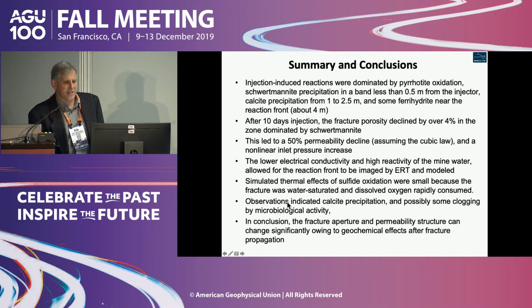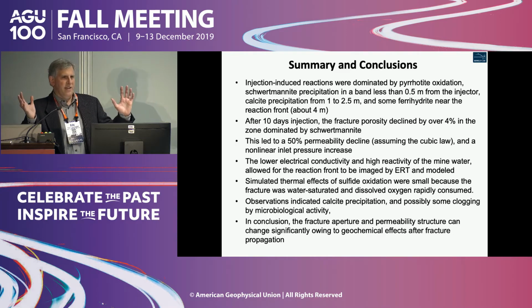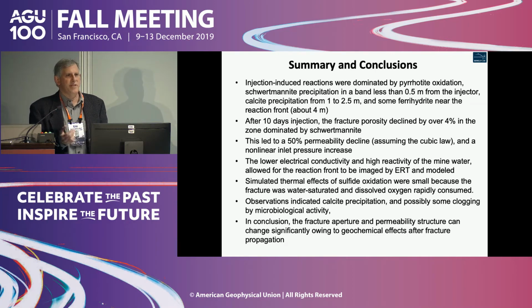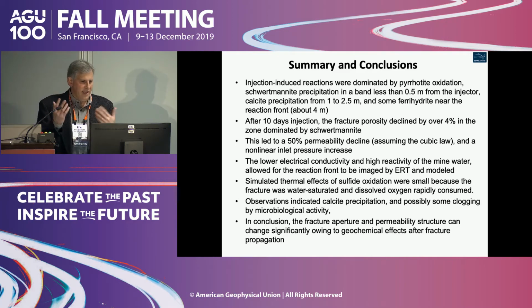The thermal effects of sulfide oxidation tended to be only a few tenths of a degree. And the reason for that is we don't have any oxygen really getting pulled into the walls. In actuality, there may be some unsaturated regions. So in our model, we assumed it was fully saturated. The only oxygen there is what you're actually injecting in. So that gets consumed pretty quickly, and the heat effects are just limited by that amount of oxygen. If there's any convection with air in the tunnel, then you can really generate a lot of heat, like you do in a mine pile.